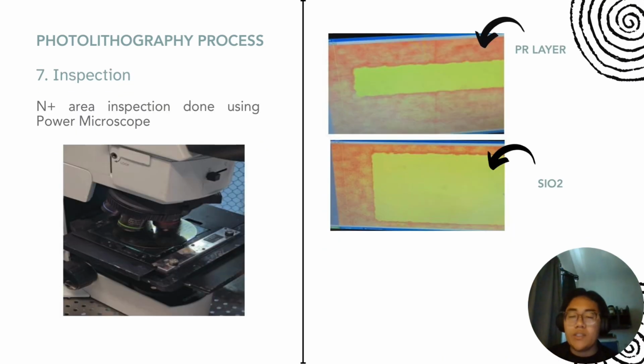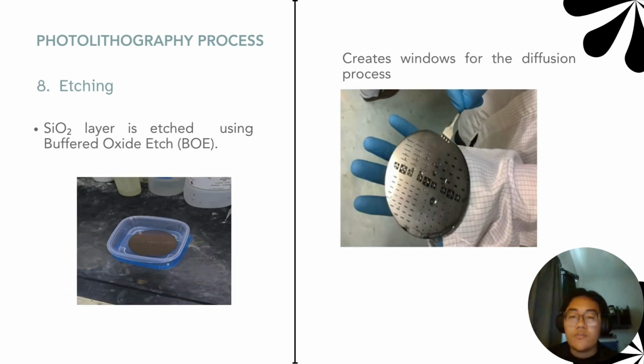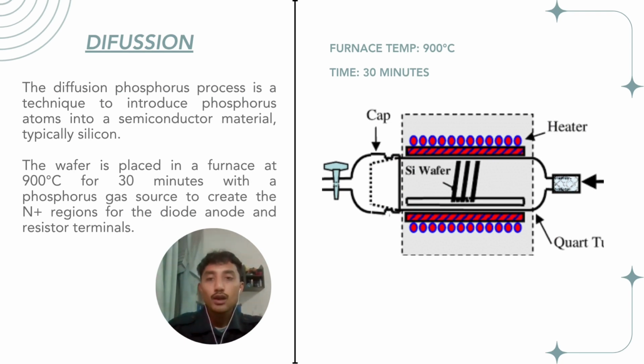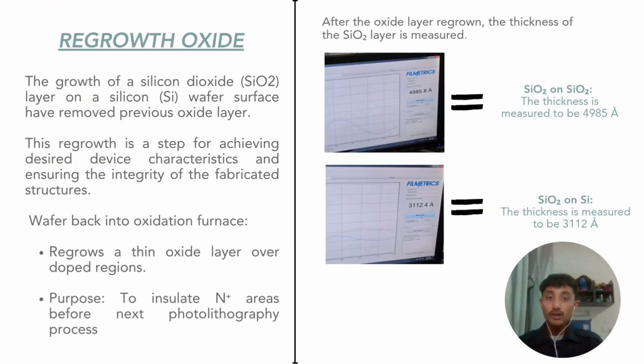Then we hard bake the wafer at 90 Celsius to fully harden the photoresist. After hard bake, we do an inspection under the microscope to see the photoresist layer and the silicon oxide layer. For the etching process, we etch the wafer using buffer oxide etch to create windows for the diffusion process. Right after etching, we diffuse phosphorus into our wafer. The wafer is placed in the furnace at 900 Celsius for 30 minutes with phosphorus gas. Then we regrow the oxide to insulate the active area before our next photolithography process. The thickness of silicon oxide on silicon measured to be 3112 angstrom, whereas the thickness of silicon oxide on silicon oxide is 4985 angstrom.